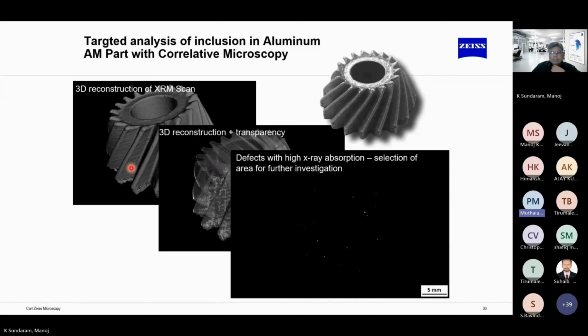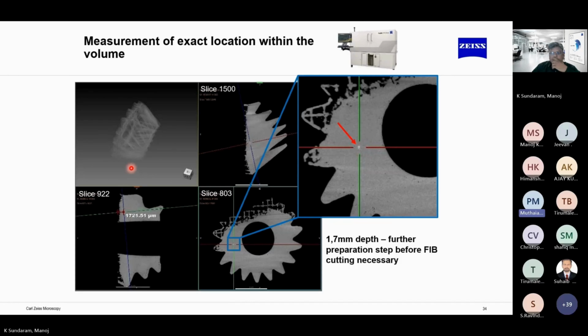So XRM, light microscope, CT, XRM, and SEM can be clubbed together for the same component, for the same region of location, without disturbing the sample to analyze. And here you can see the number of slices. The XRM data is basically built of more than 1,000 slices. So at which slice this information is available, that means at which location you have this contamination or voids, so that precisely you can go and do the cross beam application and get this EDS analysis done without compromising any information on the samples. Apparently, just a question. Is this the print slice number, the 3D print slice number, or is it the XRM slice number?